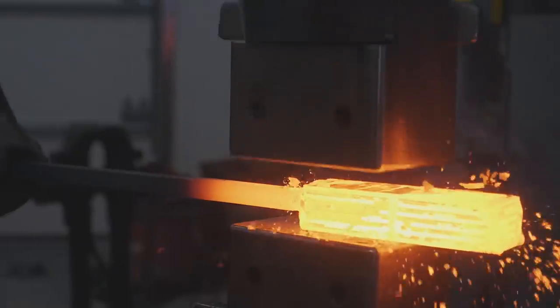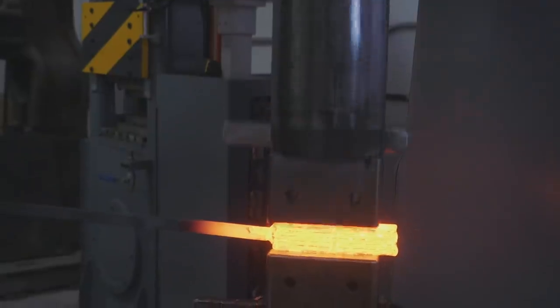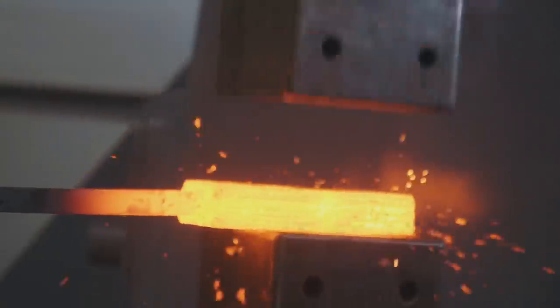since we found out that we decarburized out all of the carbon out of our iron. We think it has something to do with the phosphorus content in the wrought iron itself. Either way, we decided that we're going to mix it in with some 15N20 and 1080 steel, so that we could make a billeted Damascus where the carbon content would migrate across and end up with a really, really nice piece of sword steel. That is the hope, and we have a lot of Damascus forging to do today.